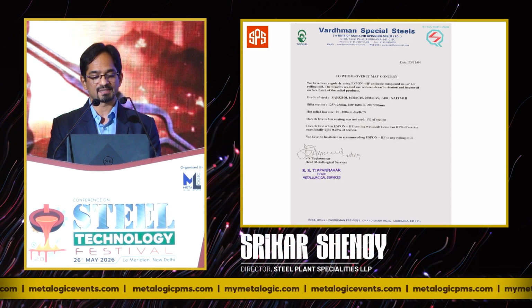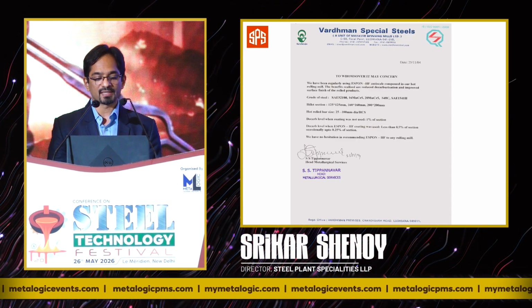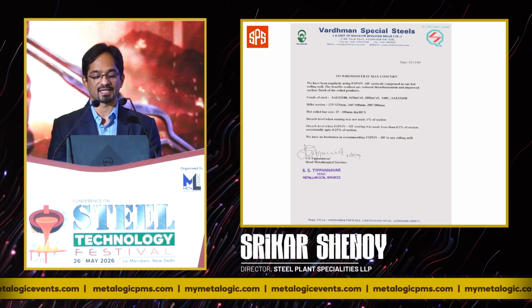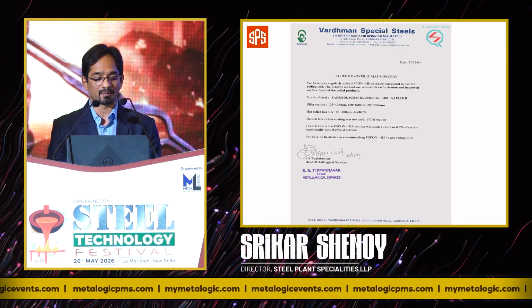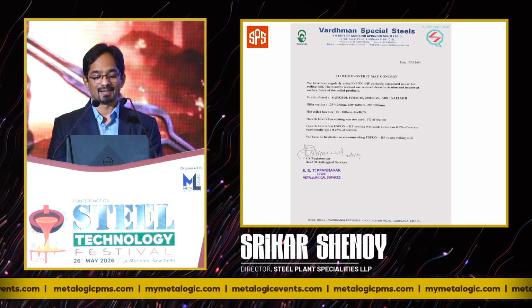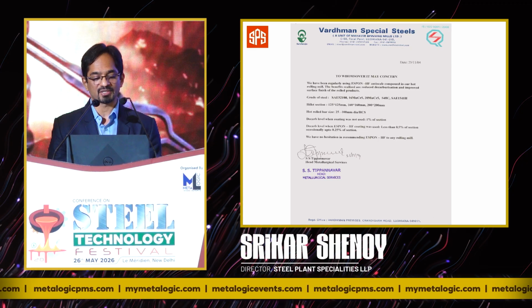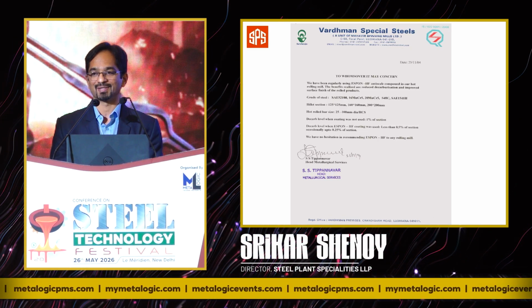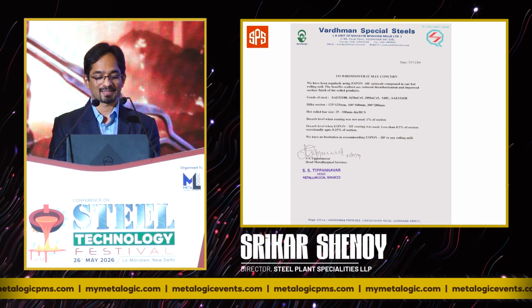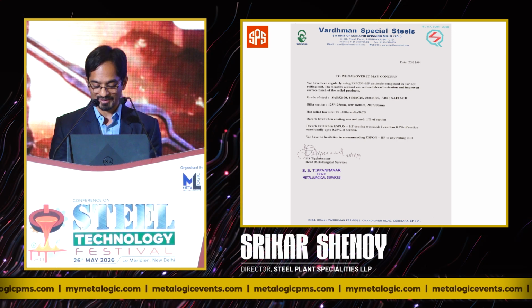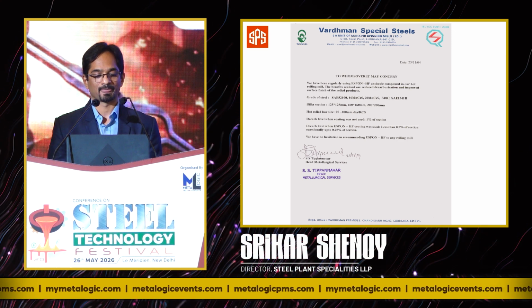What they've mentioned here is that when the coating is not used, 1% of the section is susceptible to decarb. When the coating is used, less than 0.5% and occasionally up to 0.25% of the section is decarburized. So again, like I said before, a 50 to 75% reduction in scaling and decarb.